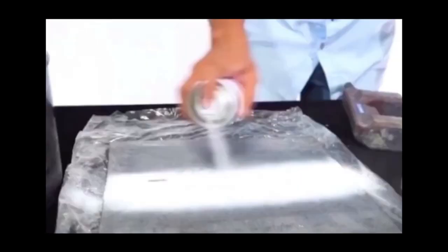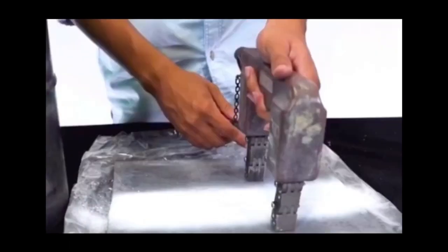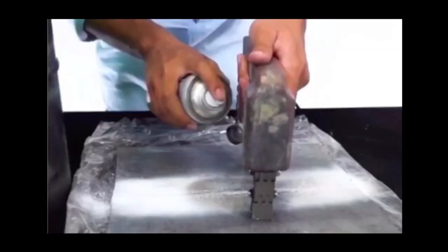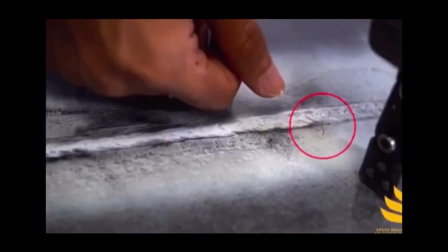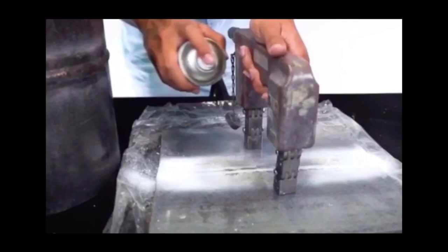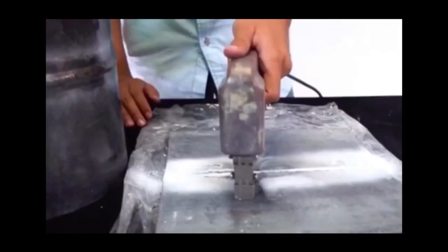First, spray the white contrast on the wheel surface with a distance not more than 6 inches away. Then, place the yoke against the wheel that has white contrast while at the same time spraying black oxide on the white contrast. Make it a layer on the wheel. Observe the wheel surface to detect the crack or discontinuities on the wheel. Keep doing the same movement of the yoke with different angles until it covers all the surface of the wheel. That's all the steps for magnetic particle testing.